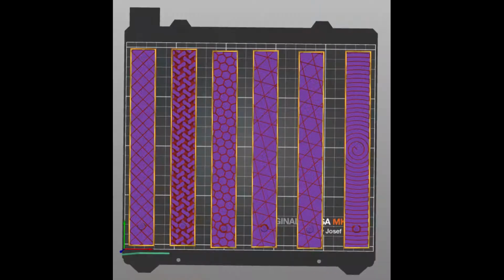The results of the experiment show that the stars performed the best and the Archimedean spiral performed the worst. This was determined by comparing the calculated Young's modulus for each of the patterns. We predicted the honeycomb pattern to perform the best based on knowledge that honeycomb patterns are commonly used in designing. We also predicted that the Archimedean spiral pattern would perform the worst because the lines are perpendicular to the length of the beam rather than parallel. The latter prediction was correct, but the best performing pattern is the stars.